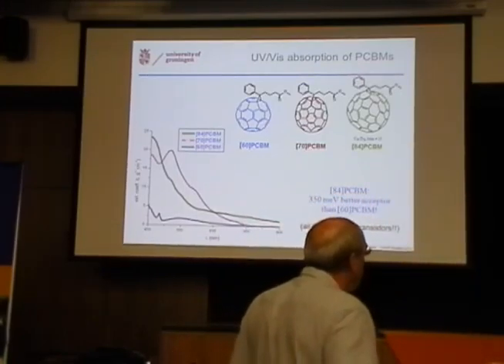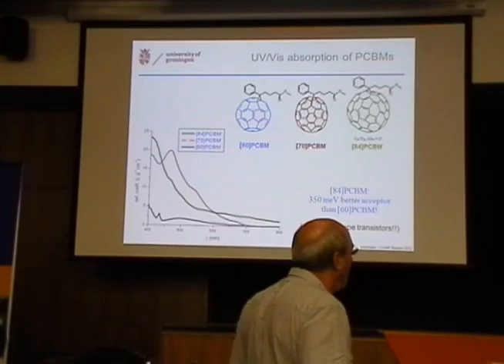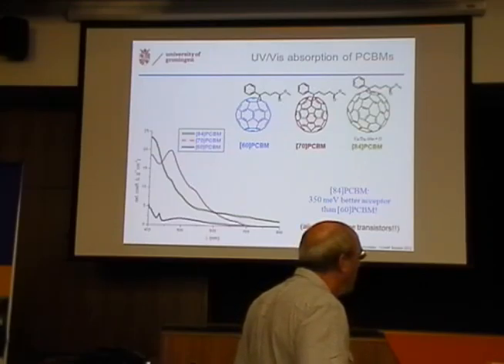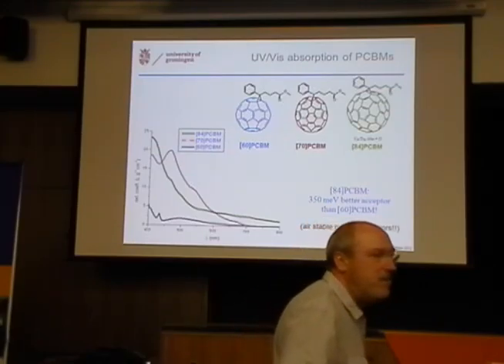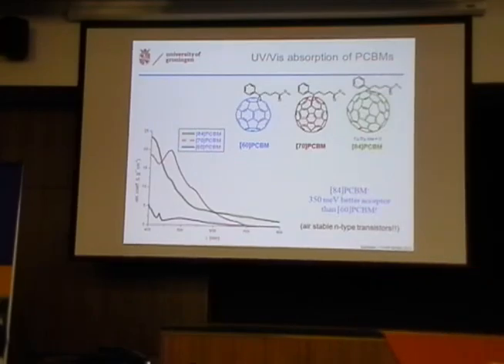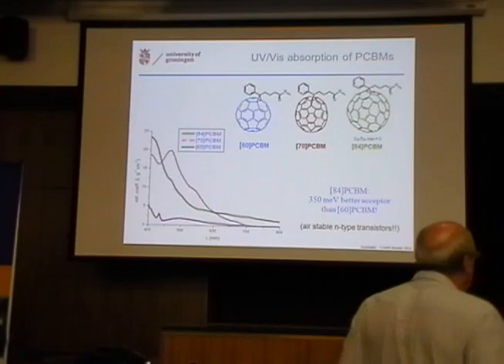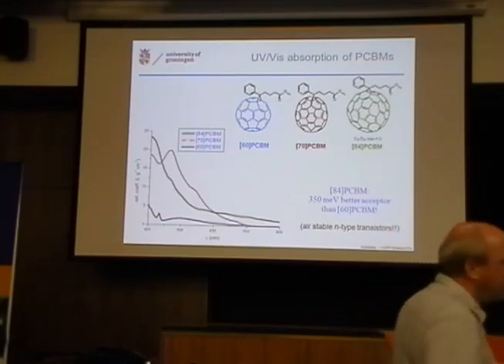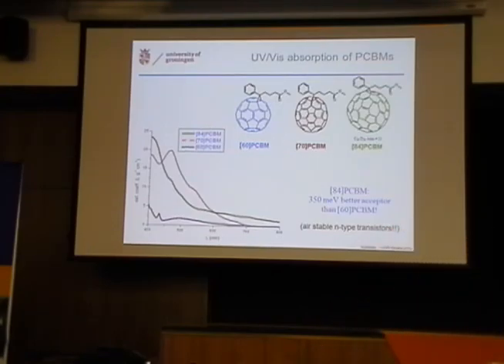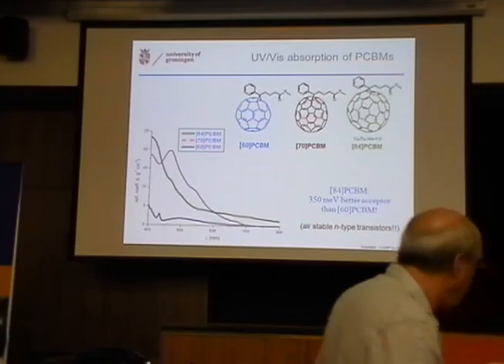But nevertheless, when you have C84, that's the next fullerene, you see that the absorption never ends. You have a band gap of 0.5 eV or something. It's really horrible, so it's no good. The only two interesting fullerenes are C60 and C70, and the mostly used material is PCBM.